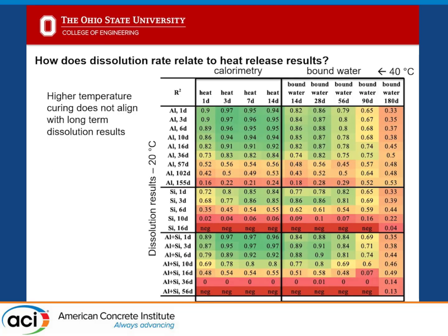Okay, that's good. And then finally, I did also want to see how the dissolution results relate to calorimetry and bound water results. And what you can see, the green is the good stuff. I should have said that on the last slide, but we see a pretty close relationship between dissolution results and the other R3 methods at early ages, and then it turns red at later ages. So this suggests what you might have already guessed. Dissolution plays a heavy hand in reactivity at early times and early ages, and then we need to start integrating consideration for nucleation and growth processes after that.